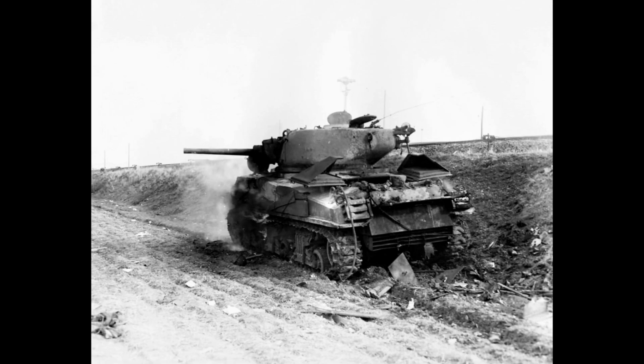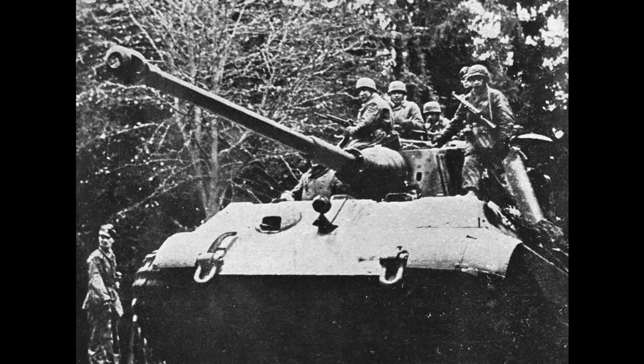The modified Sherman, now carrying 4.5 inches of frontal armor at 47 degrees, offered effective protection equivalent to 130 millimeters of line-of-sight thickness. On paper, this matched the factory-built jumbo. The critical question remained unanswered. Would field-welded, appliqué armor, applied under improvised conditions with salvaged plates, actually survive combat? Or would the welds fail under the shock of high-velocity impacts, turning the added protection into deadly shrapnel?